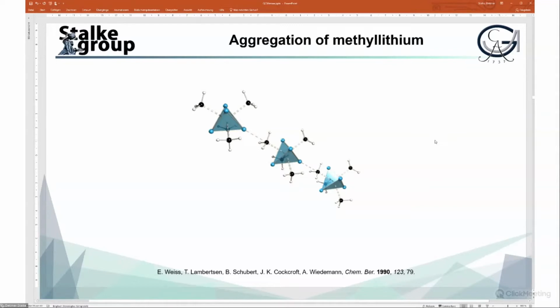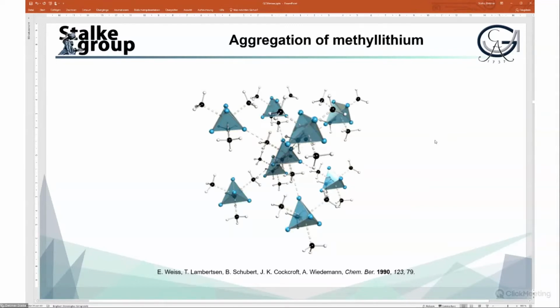If we do that with the 3 other methanides as well, then we build up the elemental cell of methyllithium, which is a cubic inner-centered cell. The tetrahedron in the middle is then connected via long-range interactions to all the neighbors.